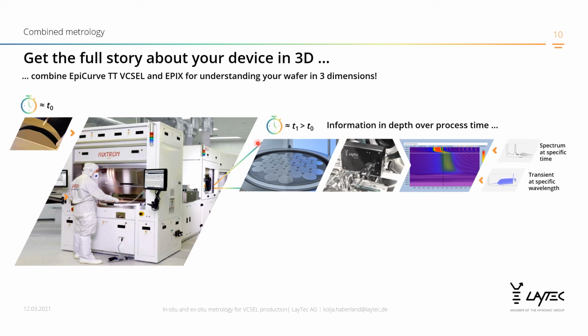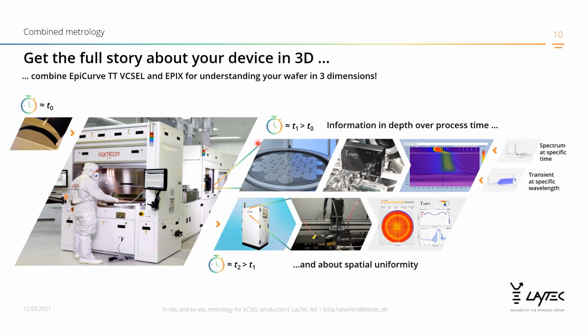And this knowledge is available at the time when the wafers are loaded after the epi run into the mapping system. So the depth information over process time is already known, and this can be used as additional information for the interpretation and analysis of the uniformity that is measured by the mapping system. Only by combining these two pieces of information, a comprehensive three-dimensional growth analysis can be performed, and you are provided with much more valuable data than just by ex-situ mapping or just by in-situ metrology. So it's the combination that makes the metrology really valuable.